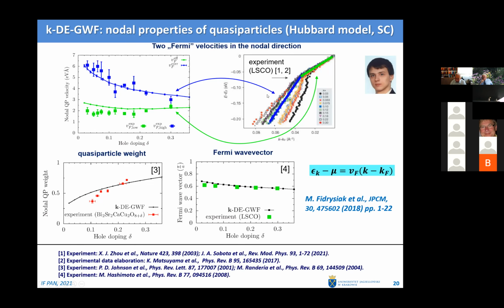And you can, so this is in electron volt angstrom units if you multiply it by Planck constant, this Fermi velocity here, and it's second Fermi velocity. And so surprisingly, from our theory, this break comes in, and it's also beautifully recovered by our theory, including in higher order correlations. Of course, previously I was showing static properties. This is also static properties, but dynamic in the sense that it describes the electrons moving around.